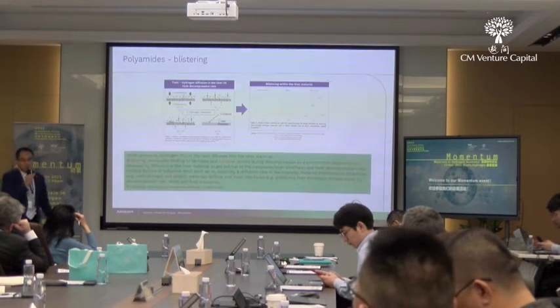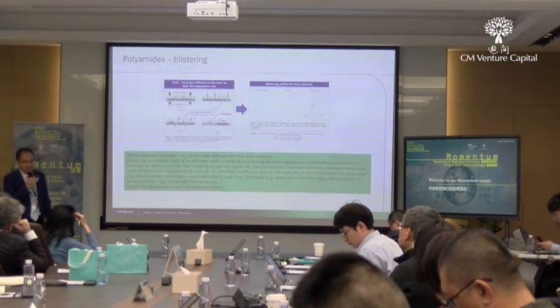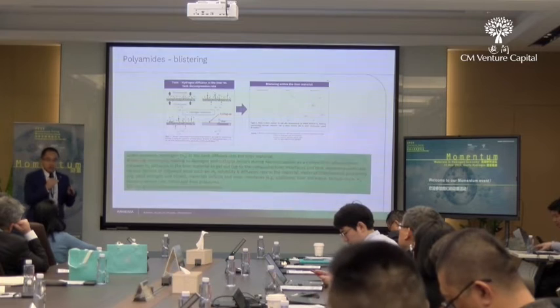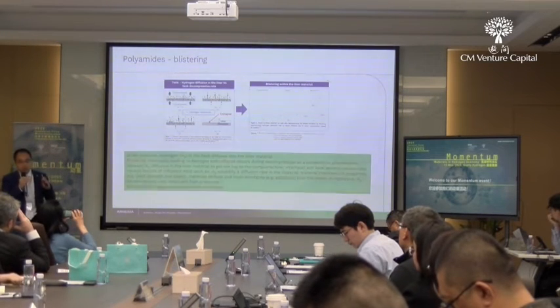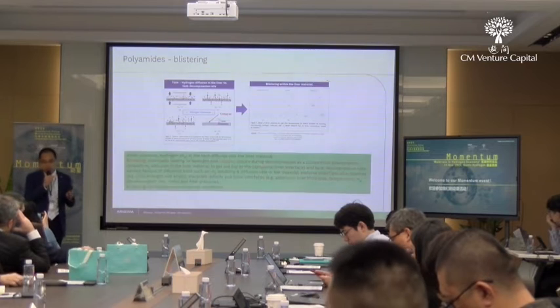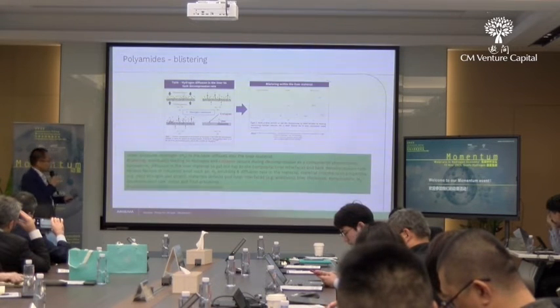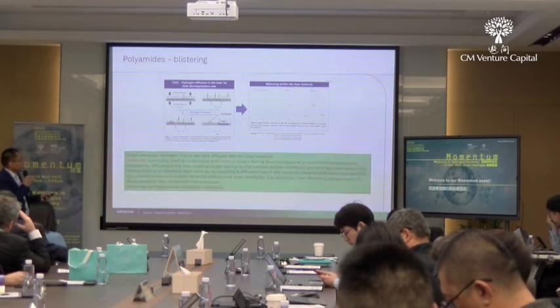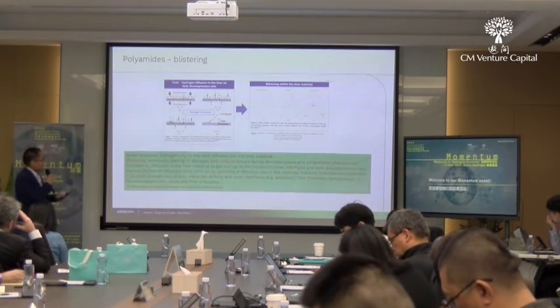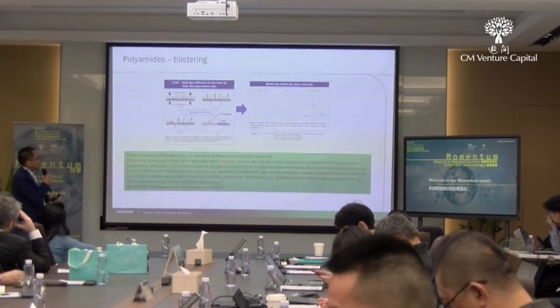Another important phenomenon in the tank is blistering. Maybe very few people talk about this topic on the market, but Arkema believes that blistering will be the key when you evaluate the material in high pressure situations, especially when your products are impacted by rapid decompression, which means that the pressure goes down to a very low level at very fast speed. It will create some kind of blistering or collapse. The difference between the collapse and the blistering is that blistering will occur only in the polymer, but the collapse will happen between the polymer and the tank composite, like the composite we use.